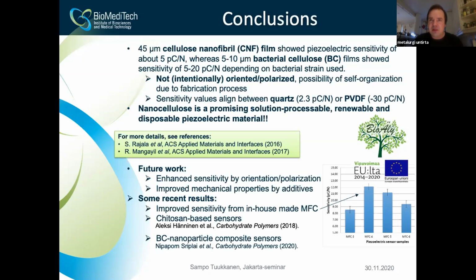It's also a polysaccharide, as cellulose and chitosan are both polysaccharides. They both have a crystalline structure. So chitosan itself is also piezoelectric. But in that paper I mentioned, we made a film only from chitosan, only from nanocellulose, and also a mixed film. You can check it out.